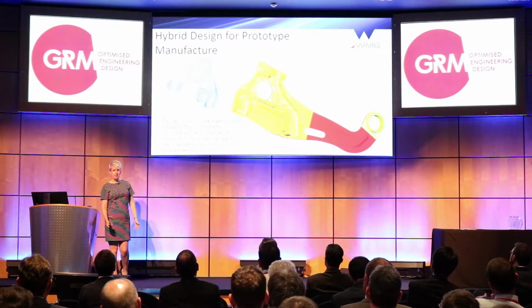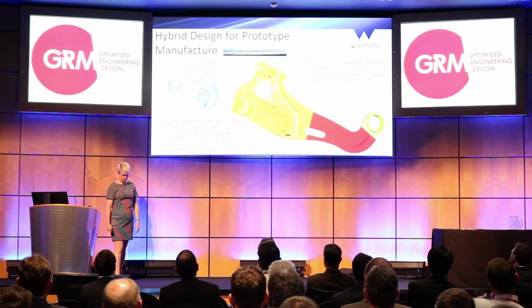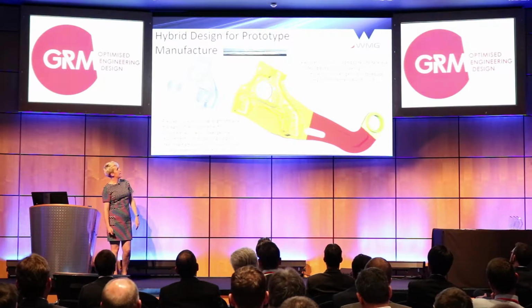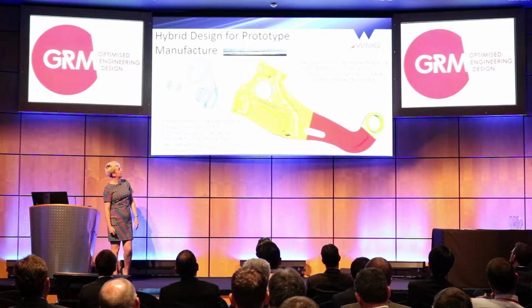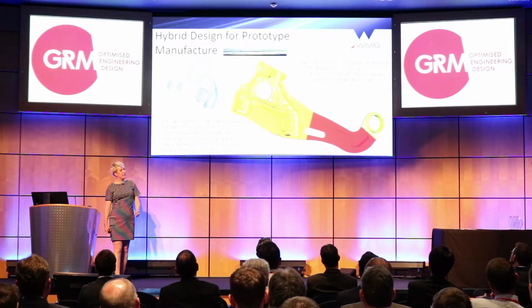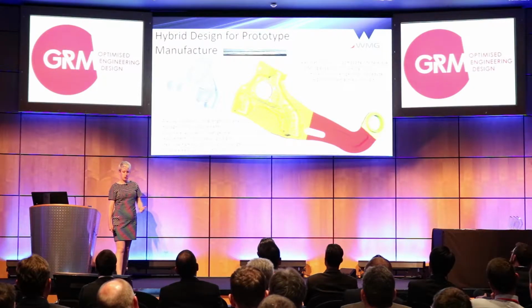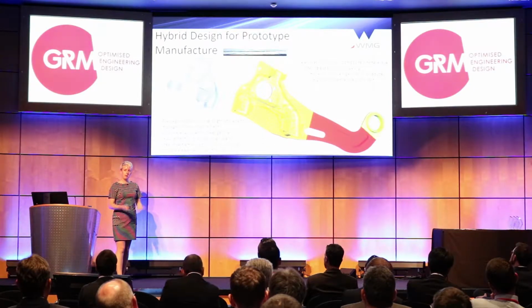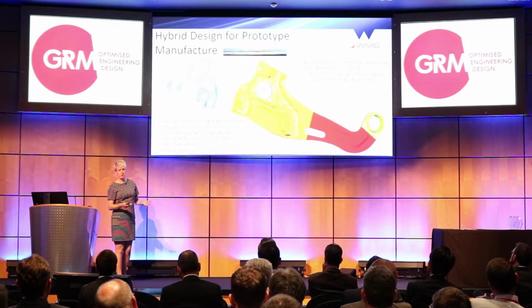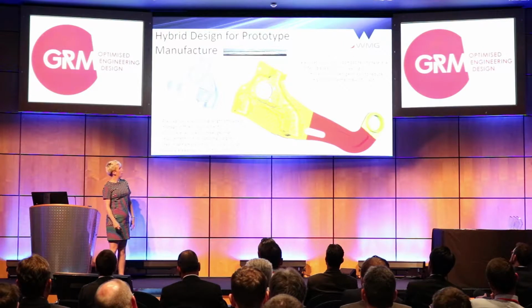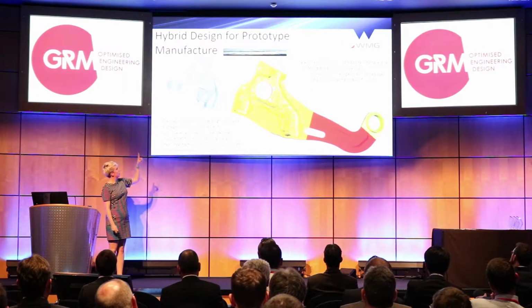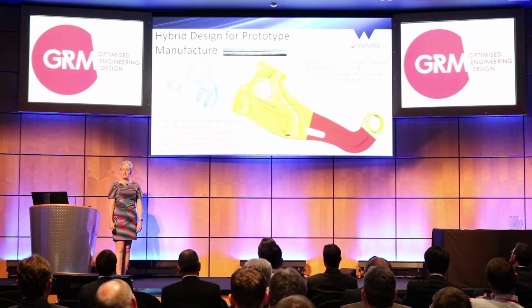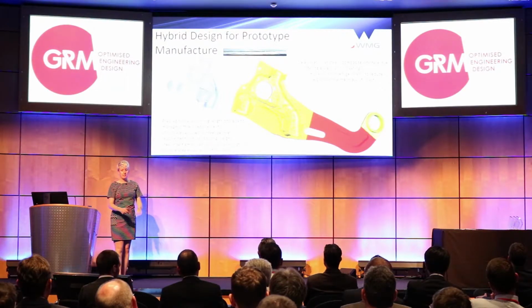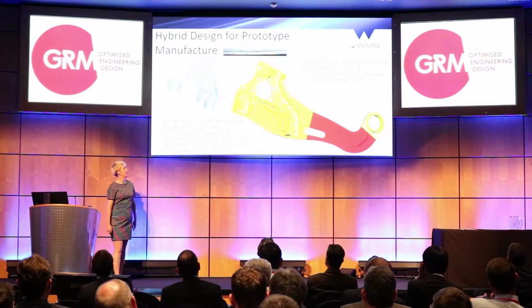Of course, there are challenges with combining steel with composites. One of these was we saw delamination at the steel composite interface. This delamination, one of the reasons we thought, was due to differences in thermal expansion. So we're moulding at 150 degrees C and then cooling down to room temperature. As they cool down, the composite doesn't shrink as much as the steel does, and you get delamination. One of the ways to reduce this was a honeycomb structure introduced into the steel insert.